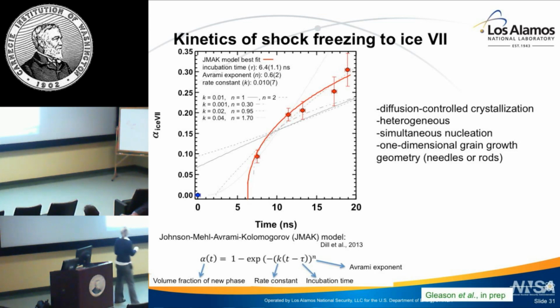Moreover, this exponent, often referred to as the Avrami exponent, is commonly tied to mechanism or transformation pathway. How is it transforming? Typically, a value somewhere between 3 and 4 is associated with diffusion-based volumetric growth, right? So there's also some geometrical, yeah. Sorry, can you clarify how you get a phase fraction when you have one crystalline phase?